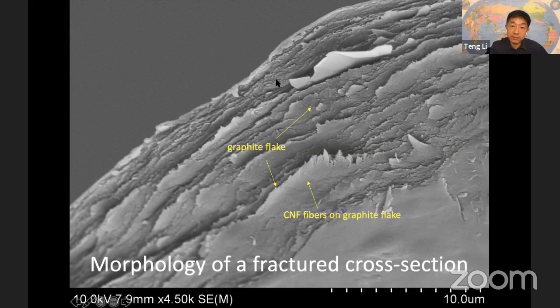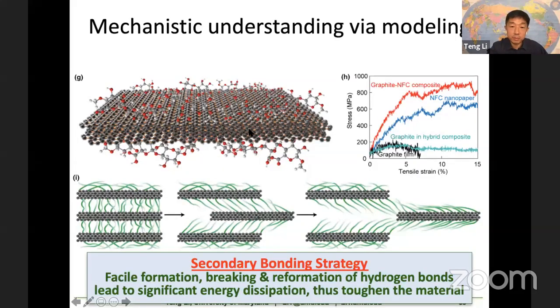As you can see, this is the SEM image of the fractured surface of this material. You see it is a very densified, layered structure, where you see this very thin layer of graphite with the cellulose nanofibers wrapping around the flakes. In this page, I show you the deformation and the failure mechanism of this material.